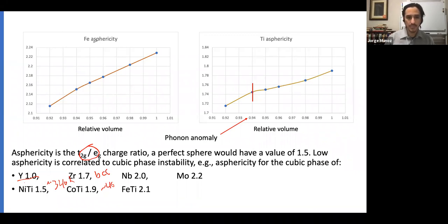When we reduce the volume and increase the pressure in iron titanium, we see that the asphericity does decrease. If we continue compressing, it is likely that at some point it will go into a hexagonal structure. Although we tried a pretty high pressure, 55 GPa, it's still not even close, but at some pressure it might.